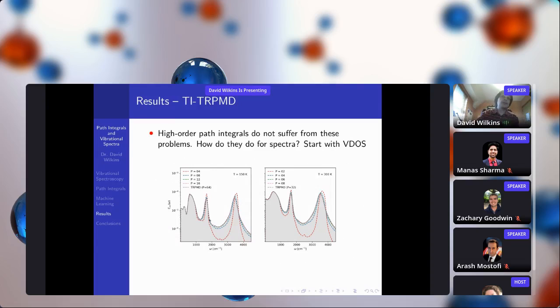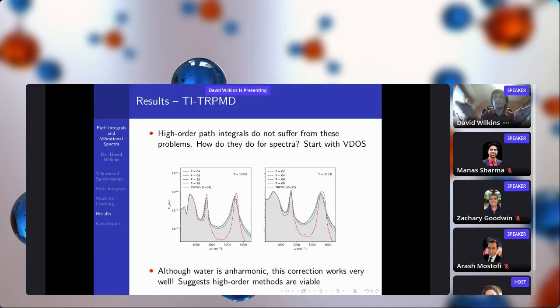Firstly, we start with the density of states. Again, the gray curve is what you get from ring polymer dynamics. And all of the other curves show what happens if you take TI ring polymer dynamics and use more and more beads. And what you see is that we can converge on the ring polymer dynamics results, and we can converge on it using much fewer replicas than we needed, sorry, P is actually what I've called N in previous slides, my apologies for that, than we needed before with ring polymer dynamics. And this is great. Even though water is not a harmonic substance, even though it's anharmonic, this correction where you take the disturbed dynamics and redshift them back works really well. So perhaps high order methods are viable.